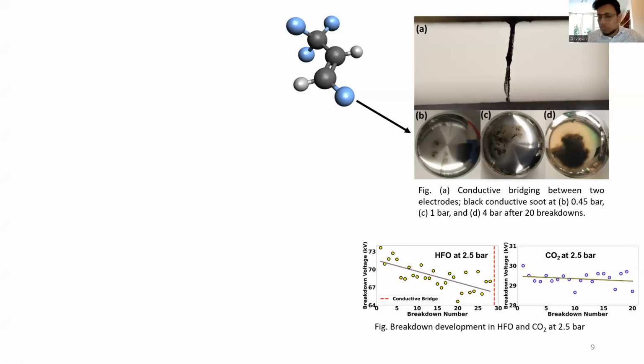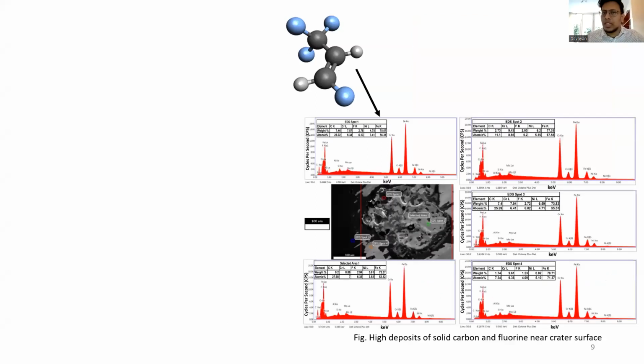So now we come to the graph, which is super important for this. But before that, for the HFO, we also did the analysis of the solid decomposition products, because for SF6 and others, we really didn't see any byproducts of fluorine, even though it has fluorine. But for HFO, you really had high deposits of solid carbon, which you expect, and also a high amount of fluorine near the crater surface as well. Solid fluorine reacts with hydrogen, and if you have fluorine gases as well as solid fluorine, it forms HF, which is very harmful. So I'll not go into the details of each of the graphs, but what you can interpret is that there is a high amount of solid fluorine near the craters.